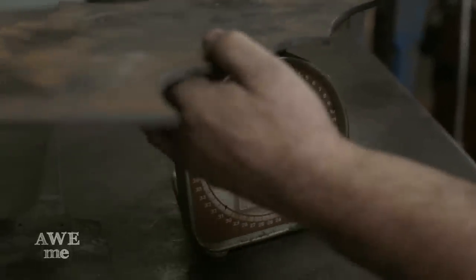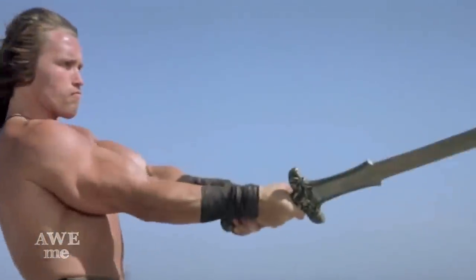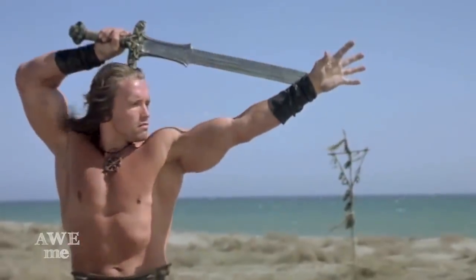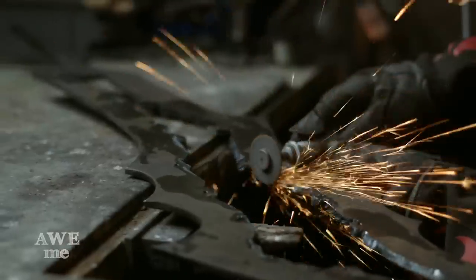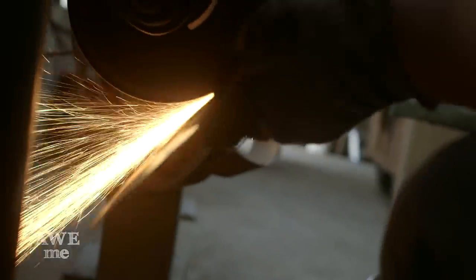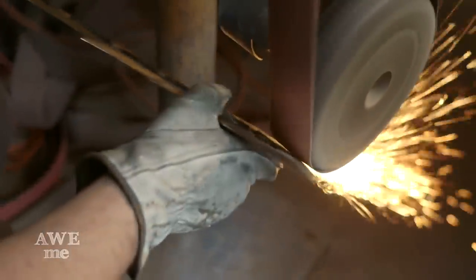Prior to cutting out the inside, skeletonizing them, they weighed 13 pounds. So, to give you an idea, the Atlantean sword that Arnold Schwarzenegger swung around for the first Conan movie weighed 8 pounds. After cutting out the inner section, it was down to 8 1/4 pounds, and I started grinding the bevels on the edge, the cutting edges, probably about 1.5 to 2 inches back, and I think it's down to about 7.5 pounds with most of it ground, so 7 pounds will have just disappeared in grinding dust.